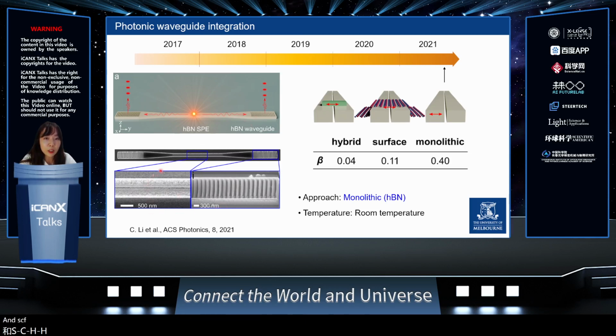SEM images of the hBN monolithic waveguide are shown here, with a slot waveguide at the center. This monolithic approach allows for a high emitter-to-waveguide coupling efficiency, defined as beta here. From left to right, the schematic shows a nanocrystal on a waveguide, a 2D monolayer on a waveguide, and a monolithic waveguide with a light emitter embedded. As you can see, the monolithic approach here can achieve a coupling efficiency of more than 3 times that of the other configurations.